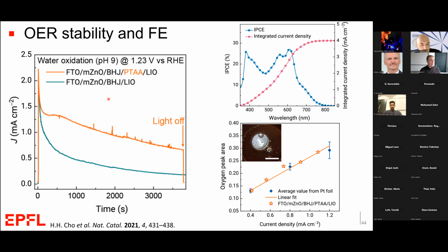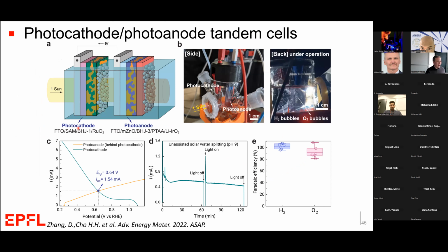And as a final step, we can put everything together: our photocathode with bulk heterojunction organic semiconductors, our photoanode with bulk heterojunction organic semiconductors. And we had to do a little tweaking here because the underlayer we used for the photocathode in the previous work wasn't stable at the pH 9 we're using for overall water splitting.